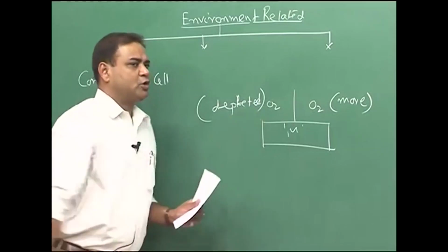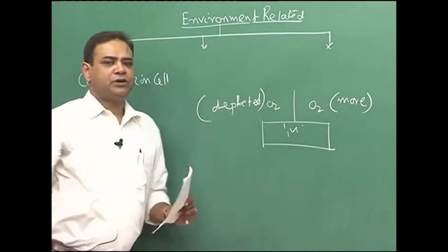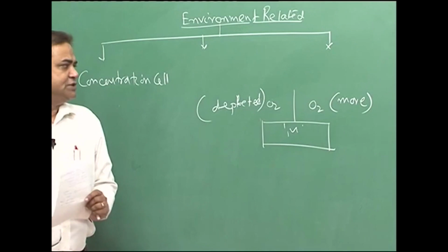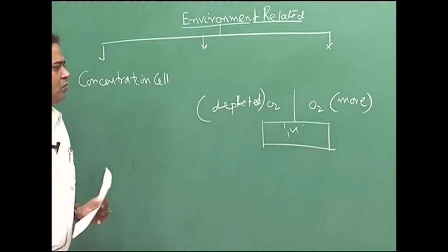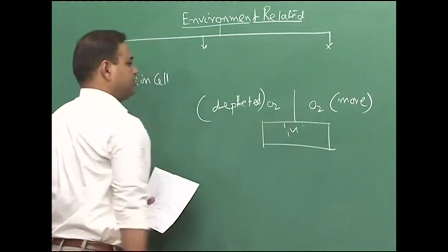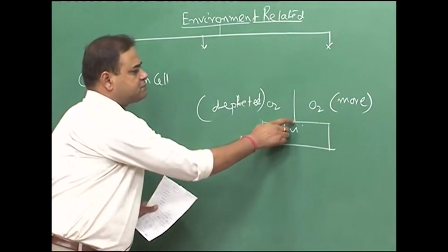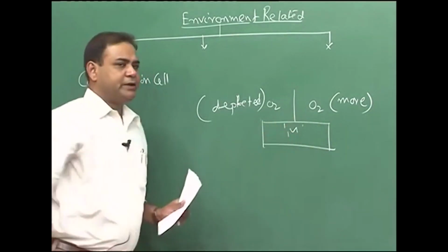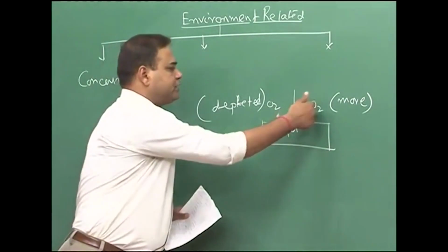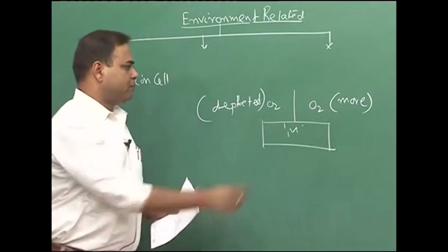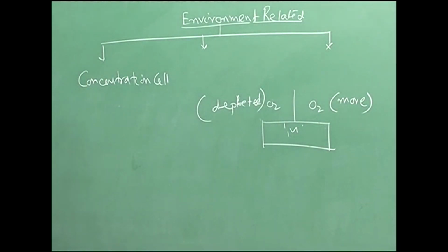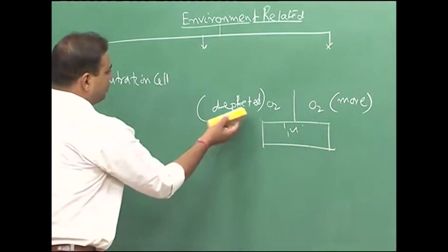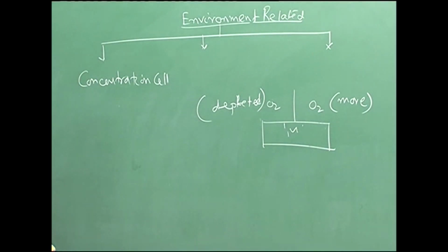And so, in this section there will be corrosion, and this is happening because of the change in concentration of dissolved oxygen. So, we are forming a concentration cell where this part is cathode, this part is anode. And so, the anodic part will corrode and this part will be protected, since the cathodic reaction will happen on the metal surface of this section. So, this is an example of concentration cell formation. We will talk about this when we discuss pitting or crevice corrosion.